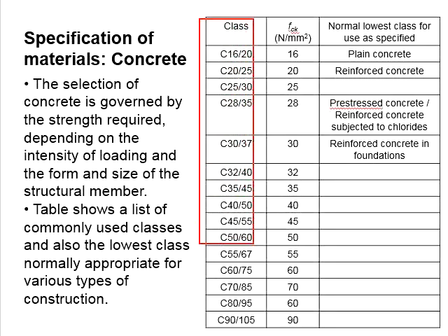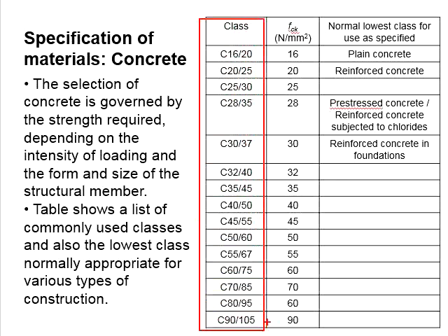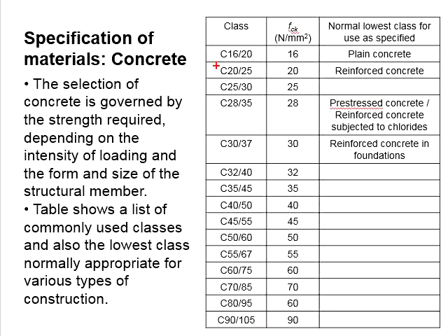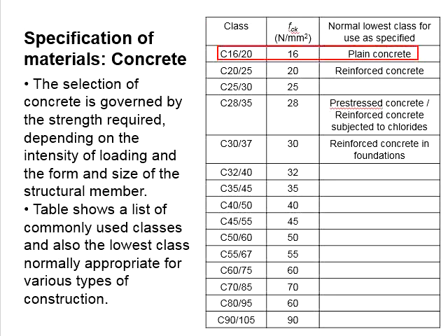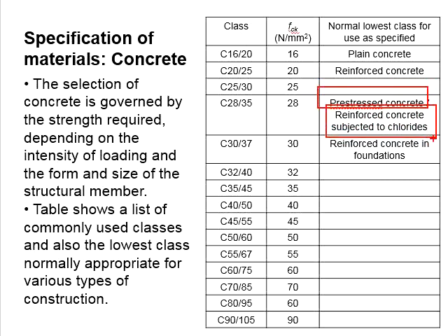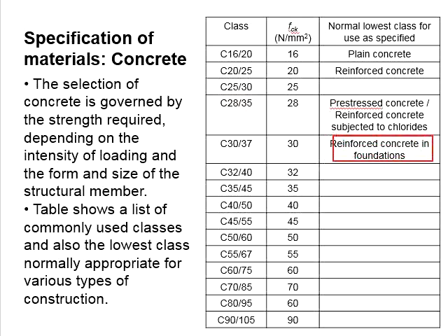The selection of the concrete class is also very dependent on the application. A typical reinforced concrete should not have a strength less than 20 fck, and below that it is typically not for structural usage. For pre-stressed concrete or reinforced concrete subjected to chemical attack, a minimum strength of 28 is used. For foundations, a minimum of 30 is used.